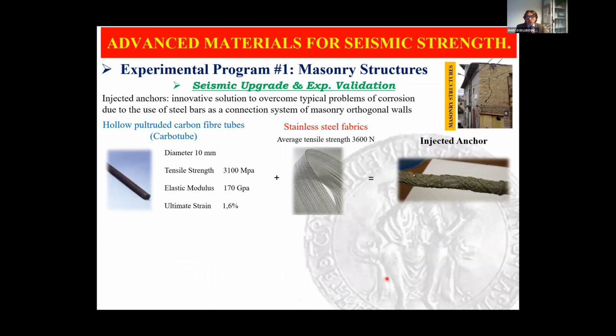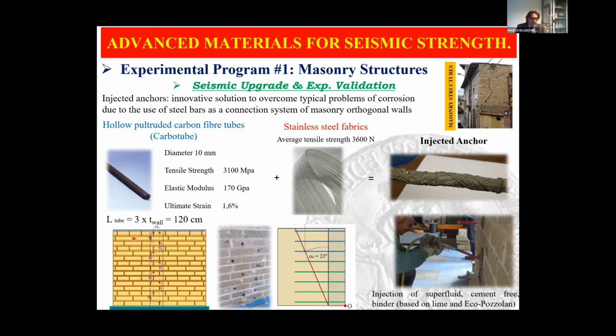overturning mechanism. So in order to increase the performance and to avoid the overturning, what we used was injected anchors based on the use of hollow pultruded carbon fiber tubes, here the mechanical properties, and then to improve the bond between the anchors and the surrounding masonry, we used stainless steel fabrics wrapped around the bar. So here you can see the layout of the strengthening solution and the bars inserted in the wall in order to connect this wall to this one.